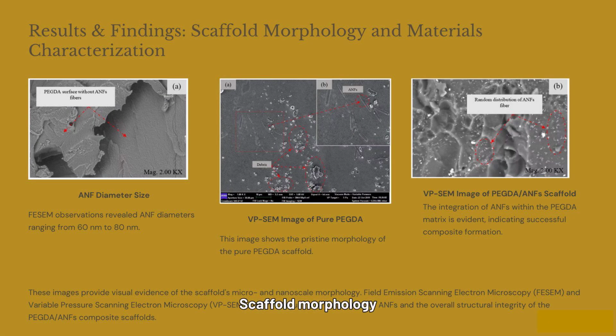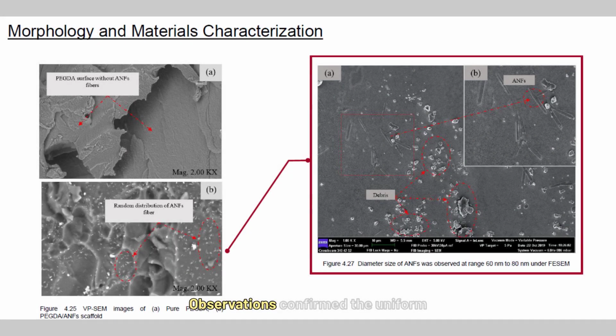Scaffold morphology and material characterization using field emission scanning electron microscopy and variable pressure scanning electron microscopy provided visual evidence of the scaffold's micro and nanoscale features. Observations confirmed the uniform distribution of aramid nanofibers within the PEGDA matrix, with ANF diameters ranging from 60 to 80 nanometers, indicating successful composite formation and structural integrity.